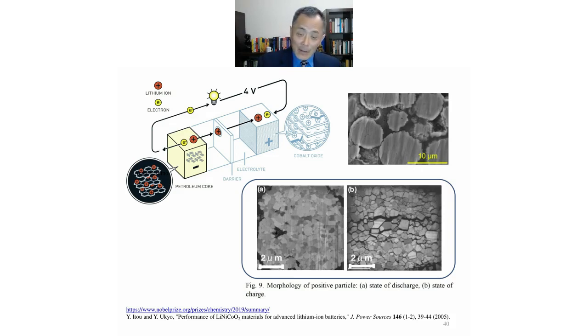As these are layered structures, as lithium goes into the layers, there is still volume expansion, although it's not as significant as in the case of silicon electrode. Nevertheless, people have found that cracking can occur inside individual particles of lithium cobalt oxides or lithium nickel cobalt oxides or lithium manganese oxides. And here's an example of it: after cycling, cracking within the particles was observed.